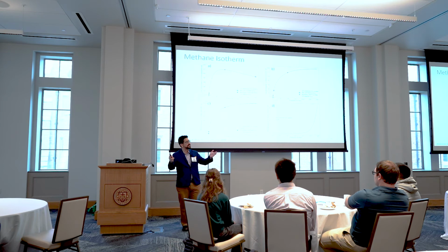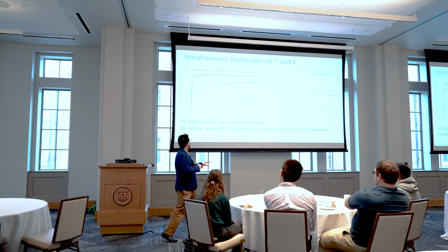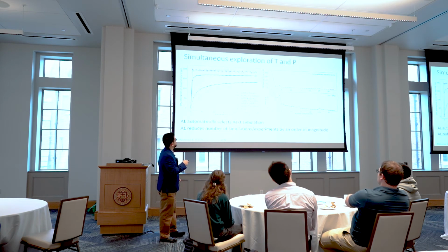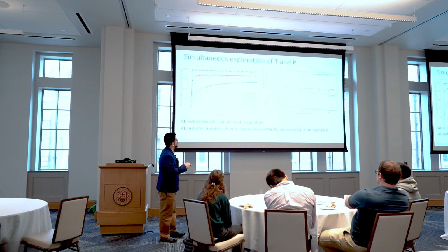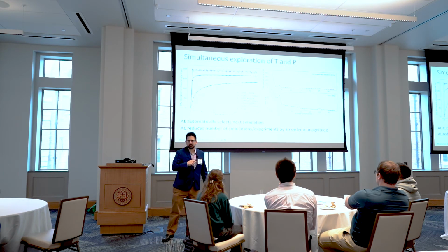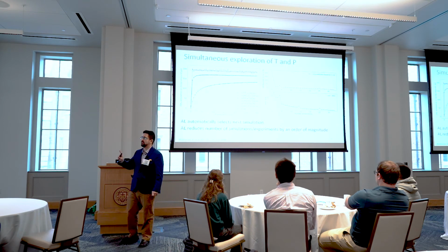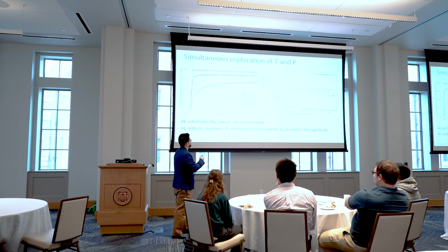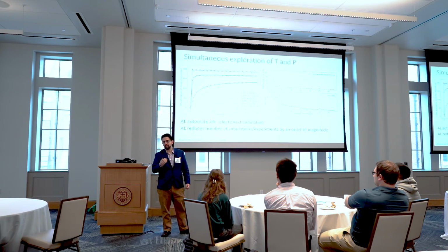I can also simultaneously navigate temperature and pressure. And so that's what we show here. Okay, so I can show you here how my error, my predicted error is changing as a function of iterations. So it's about 33 iterations, and this is then sort of the mean relative error compared to that ground truth, which is under 1%. What does that mean? With 33 simulations, I'm able to make the predictions just as accurate, essentially, as almost 5,000 data points.